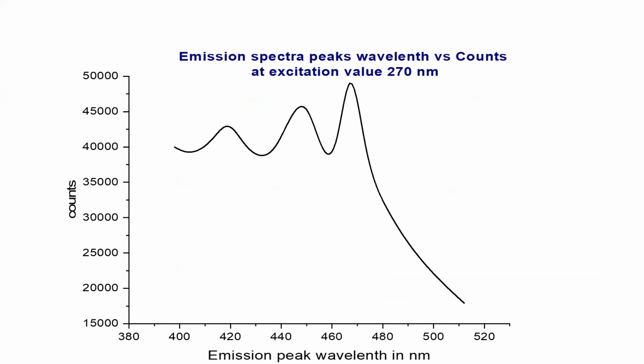On the basis of that data, I again analyzed by using some basic mathematical modeling with the Origin software. Here I found that if we excite my sample with 270 nanometer, there are three peaks showing specifically. It means in that particular range, when we excite the sample with 270 nanometer, there are three sub centers possible to emit different energies or different wavelengths. It means I am again able to say that tuning is possible due to variation of band gap. The dominant peak comes around 467 nanometer, but two other peaks are also available in that graph, so it is again possible to tune the bands.